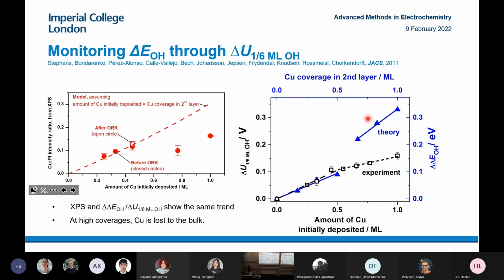So we also quantified the amount of copper that was there using XPS, X-ray photoelectron spectroscopy, as a function of the amount of copper initially deposited. This red line shows how much of the copper signal we'd expect to see if all the copper initially deposited stayed in the second surface layer. What we found is that when we put more than half a monolayer of copper, some of the copper is missing. We think what's probably happening is you're fighting enthalpy and entropy, and the enthalpy required to stabilize the copper in the second surface layer isn't quite enough at high amounts of copper, and you're losing out to the entropy of the massive platinum single crystal, so the copper is getting dissolved in the bulk of the platinum single crystal.